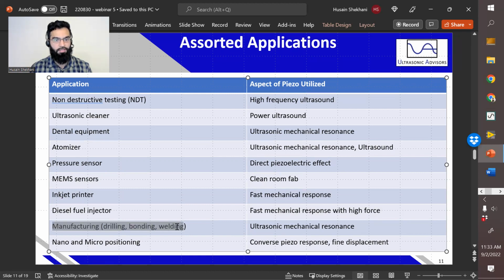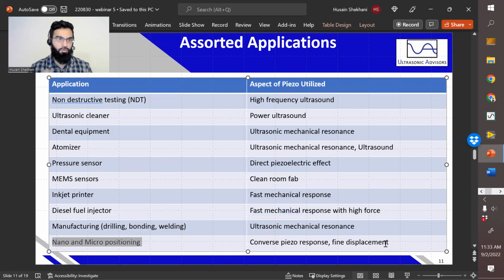For manufacturing, as I mentioned, drilling, bonding, welding, we use ultrasonic mechanical resonance to melt two materials together or weld them together using different phenomena. Nano and micro positioning: we use the converse piezoelectric effect. You apply a voltage, like you increase your voltage by 1 volt, you get a portion of a nanometer displacement. So you have very fine control of displacement, which is obviously important for specific applications.